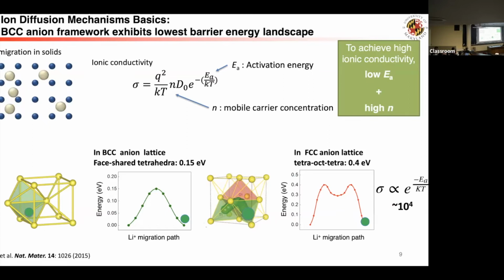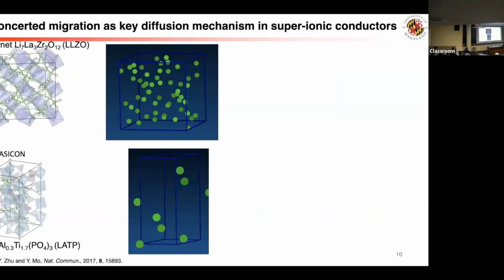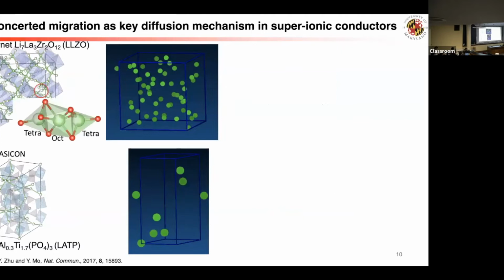Then what we do is use ab initio molecular dynamics to see how the ion diffusion mechanism really works in these fast-performing materials, because all these other good super-ionic conductors do not have this body-centered cubic packing. So in this lithium garnet structure, the lithium has this tetrahedral kind of local environment, and this is an animation from our initial MD simulation. It's freezing, so you cannot see.